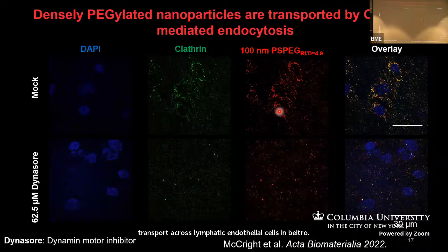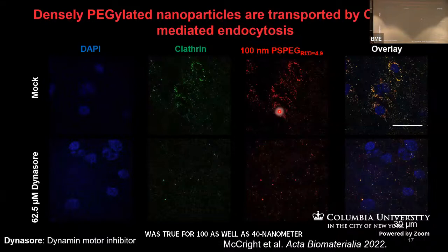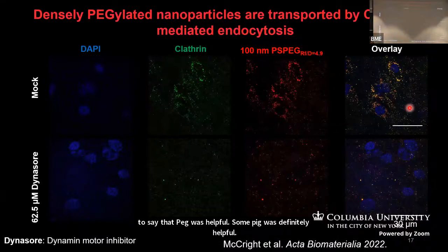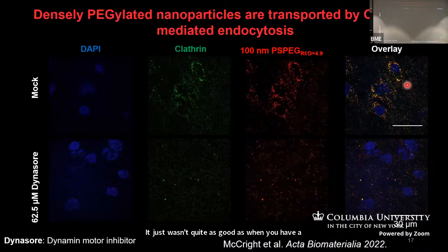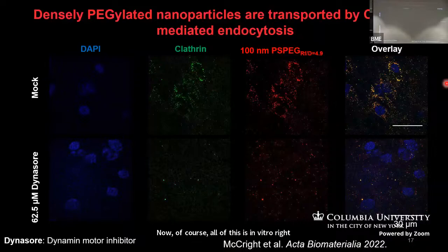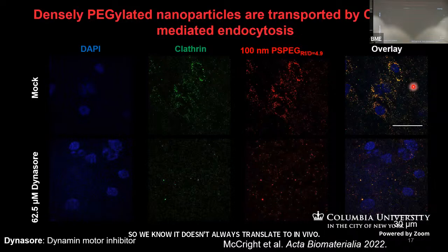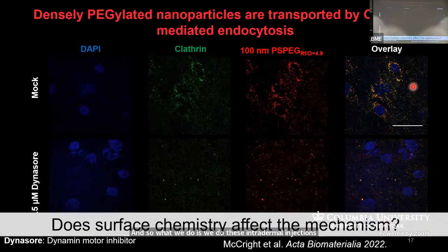And so one of the things we were looking at is clathrin-mediated endocytosis, which is commonly used by cells to transport nanoparticles. And we really found that there does seem to be some clathrin-mediated endocytosis. So you can see the yellow in the overlay here is where you have your particles as well as the clathrin-coated vesicles. But we did most of this with just our densely pegylated particles just to get a little bit of an understanding. So we really started asking, how does surface chemistry affect this mechanism?